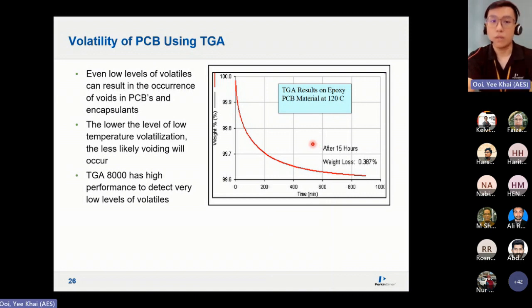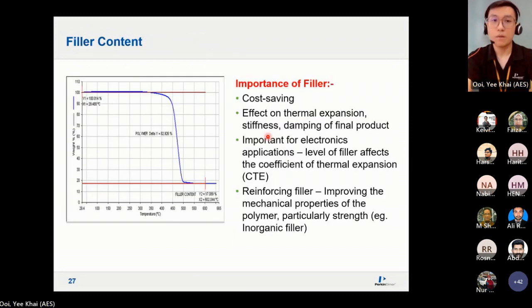Okay, so with the very, very sensitive TGA, you can detect very, very low levels of volatiles. So this applies not only to your solvent, it can be moisture as well. Okay. So the one that I mentioned just now, people use TGA mainly to check the filler content, especially in industry. Okay, so filler is something that they put into the polymer, for example, to reduce the cost or to modify the performance of the material, whether it is thermal expansion, the stiffness of it, and then the damping of the final products.